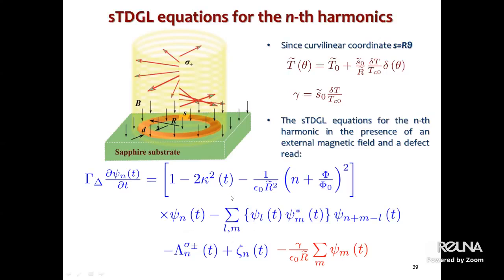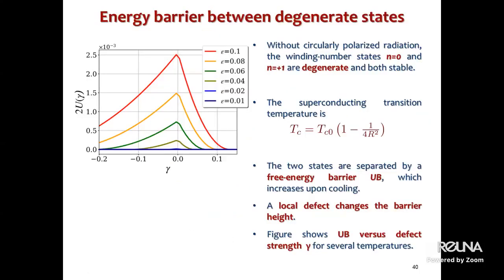Okay, now a few words about the physics in order to explain the result. Let us investigate what a local defect does. For that, it's useful to deal with the free energy of the system. As we discussed already, without circularly polarized radiation, the winding number states n equal to 0 and n equal to 1 are degenerate and stable in the absence of a defect. The superconducting transition temperature of the ring is smaller than its bulk counterpart. It's standard because we deal with a ring, so the critical temperature is slightly smaller.